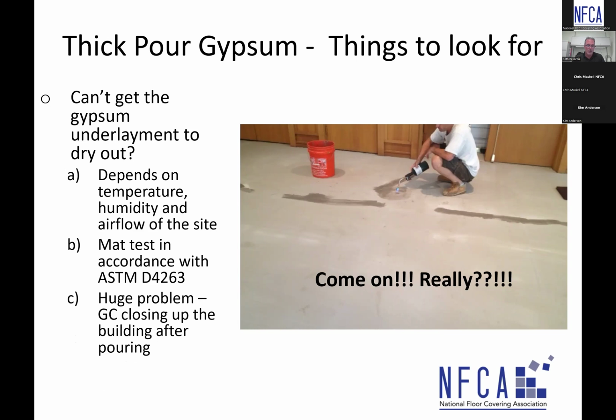And I mentioned this a little earlier too. One of the huge problems is the GC closing up the building after they pour, and they basically create a greenhouse effect, and you basically get to 100% humidity, and it's probably raining. You got water going down the windows and raining from the moisture that's collecting on the ceiling, for that matter. So we can't close the building up. We gotta have good airflow going. Good temperatures are critical as well.